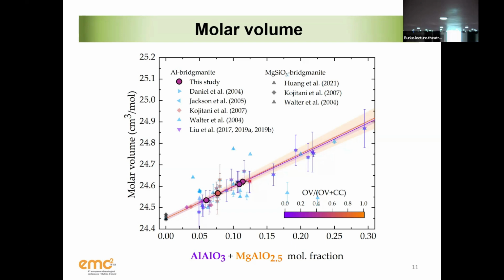So this is the molar volume at room pressure and room temperature. The first thing that we saw is that very likely this major difference between the oxygen vacancy mechanism and the coupled substitution mechanism that is present in the literature may not be so correct for samples that are representative of the mantle. They always say that with oxygen vacancy you have a much larger volume than with coupled substitution. Of course, if I use brownmillerite, I will probably have a much larger volume. But for these samples, where the gap between oxygen vacancy and coupled substitution is limited, we don't see this great difference, especially at this low concentration. Of course, if I extrapolate the two trends, I will have a much larger difference. But that's another matter. I don't know if it's linear until the end member, and I don't care about the end member because these are the compositions that we are interested in.